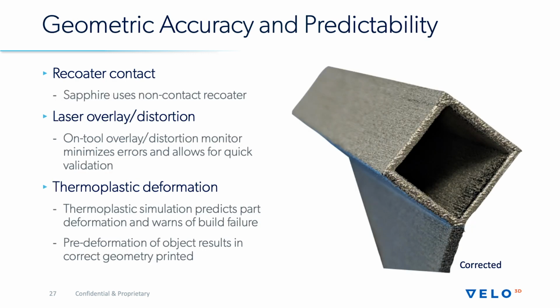And finally, in conclusion, the three areas I talked about today in terms of improving deformation correction and first print yield. First of all, on the Velo Sapphire system, we're using a non-contact recoater, which eliminates that major source of failure from many builds. The second thing is we have the ability to measure overlay and distortion before or after any build, or even during the build, to check to make sure that the lasers are well aligned in printing the correct shapes. And this allows us to quickly validate that the machine is healthy before running any prints and make sure that the parts come out geometrically accurate.